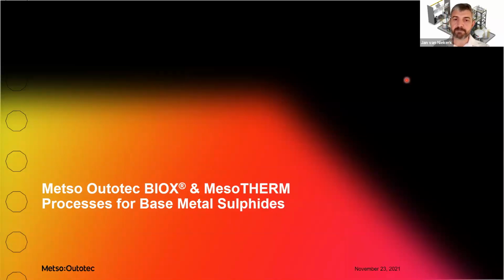of equipment. So typically for very small plants, we can see that the BIOX capital cost can be up to half the pressure oxidation capital cost. However, as you then go bigger, we see that the switchover point is somewhere between 1,000 and 2,000 ton per day of concentrate. That is where the pressure oxidation capital cost will become more competitive. And that's simply because at one stage you reach the maximum size of a single BIOX reactor or BIOX module, and then you just start to add more and more modules. Whereas for pressure oxidation, you then get that economy of scale.